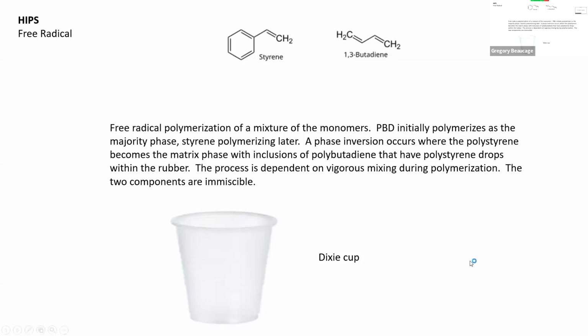But during the polymerization, it goes from a butadiene matrix with styrene monomer to a styrene matrix with butadiene. And with all that mixing, the butadiene domains have little styrene particles in them. So they're rubber domains with little glass reinforcement in them, and the rubber makes the styrene craze a lot. It's going to be kind of white, like you've seen these plastic mouthwash cups, I don't think that's really a Dixie cup. It's polystyrene with butadiene mixed in this way: high impact polystyrene.